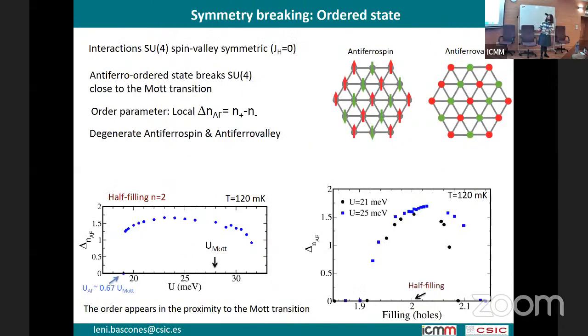So you see here, this is the interaction for the Mott transition. Below this interaction, we have a coherence peak, so the system is metallic. Above, we don't have this coherent peak. And we find in a range of parameters, both below and above, this insulating state. I have to say that I cannot say whether there is antiferromagnetism or not beyond this interaction because there were convergence problems. But if the interaction is too small, we don't find it, and that can be studied.